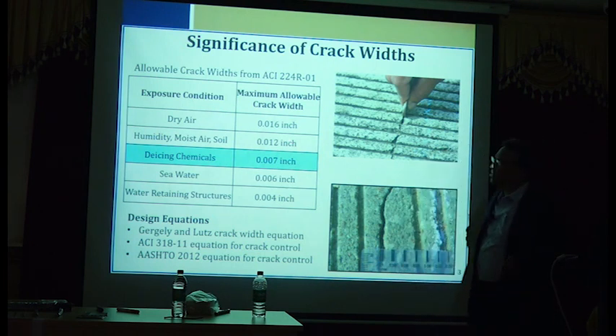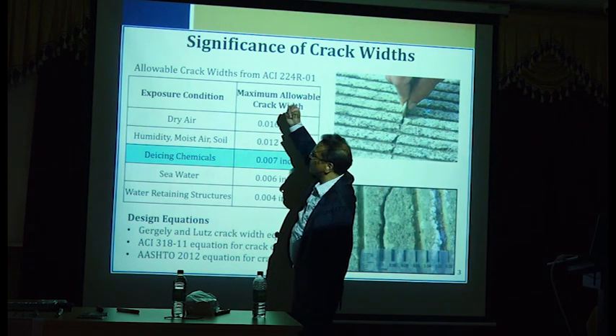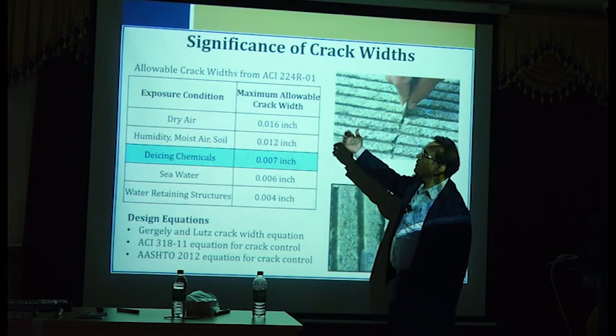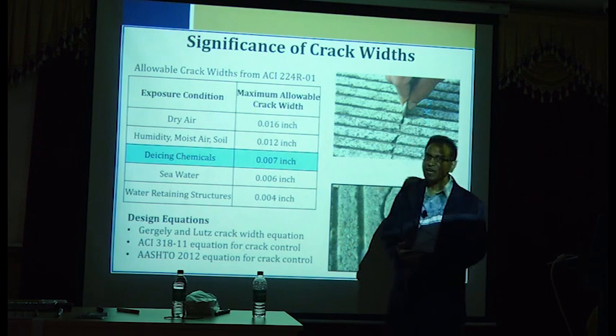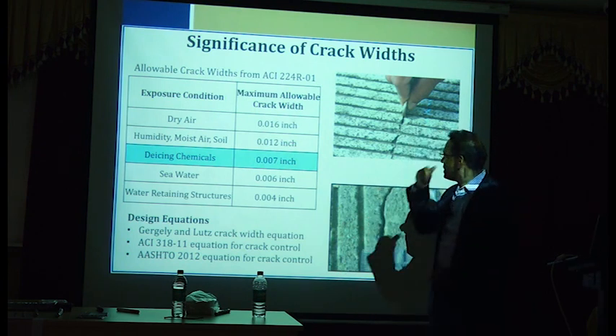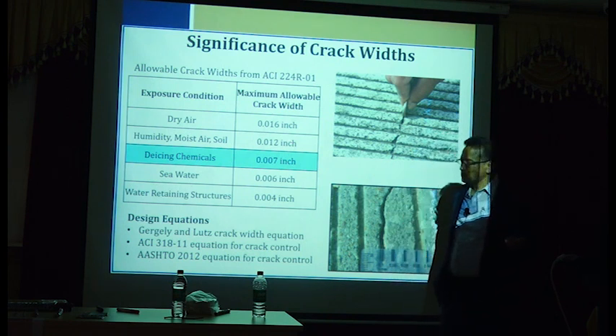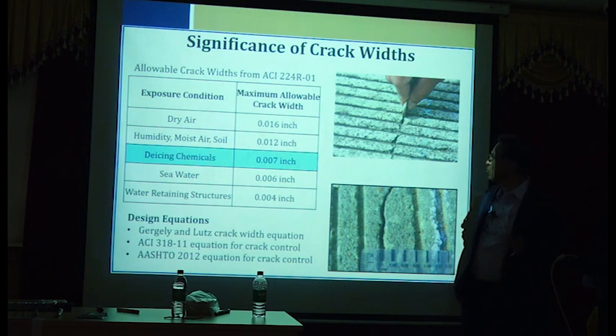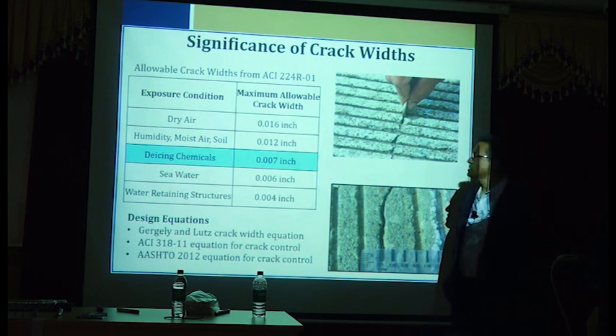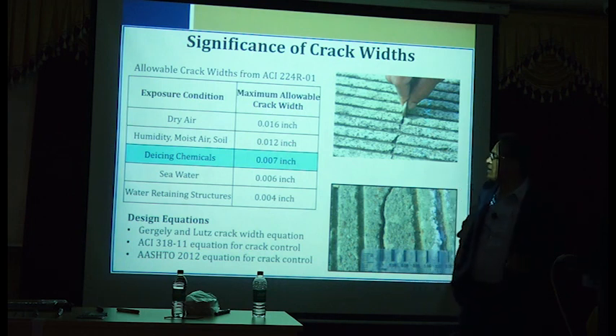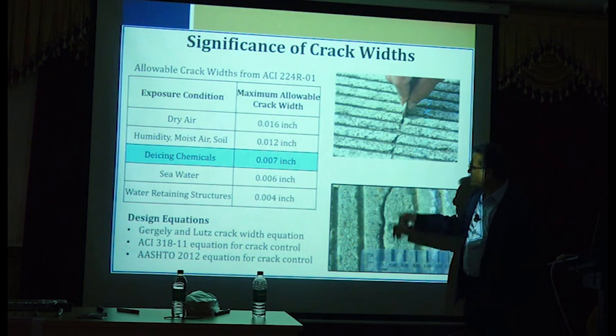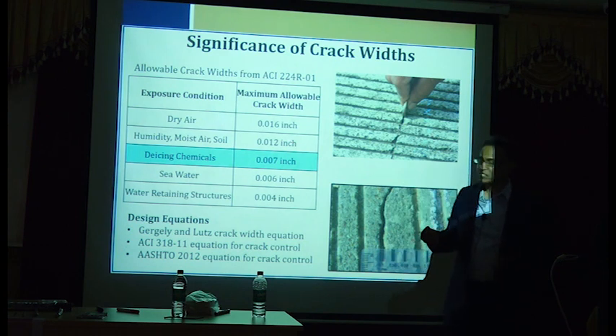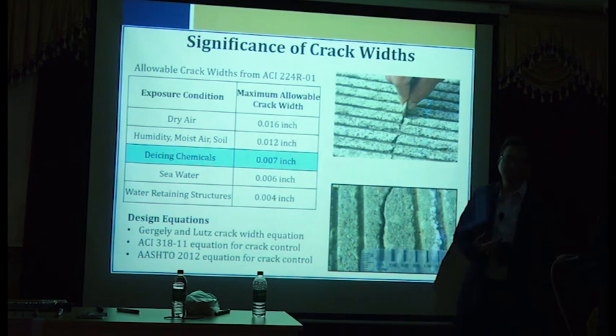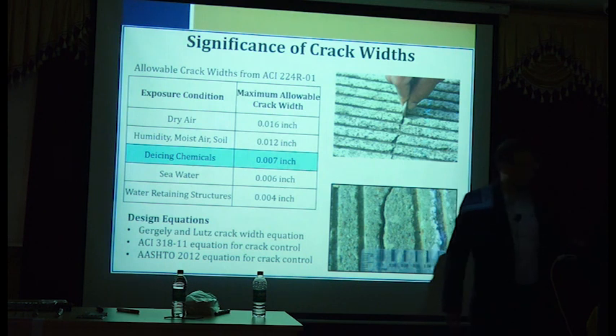So if you see ACI 224R, the recommended maximum width for this kind of cracks is 0.007 inch. And what is 0.007 inch in terms of millimeter? It's probably times 25, about 0.18 millimeter, I think, less than a millimeter. So that's very, very restrictive. I don't know if you can imagine that, but it's very, very restrictive. But in reality, on real bridge decks, we can get cracking as much as 0.1 inch. It's a lot of thickness. Okay, so that's a big problem.